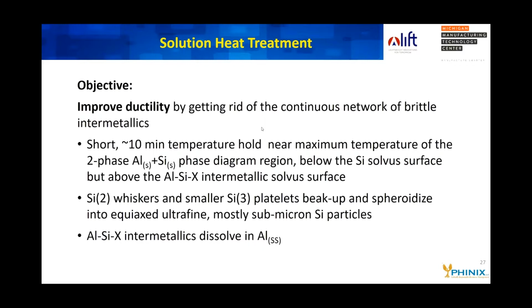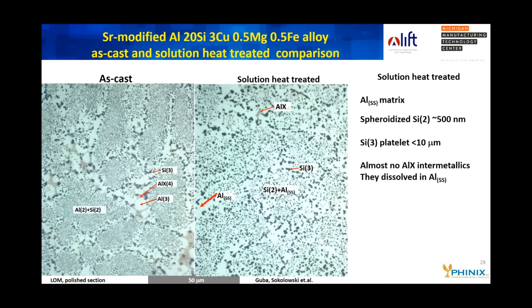So what happens is that silicon whiskers and the smaller Si3 platelets break up and spheroidize into equiaxed, ultrafine, still mostly submicron silicon particles. And the aluminum intermetallics mostly dissolve in the aluminum to form an aluminum solid solution matrix. So here is a comparison between as-cast and solution treated structure. And you can see that the aluminum now is a solid solution matrix that now contains most of the copper, and the intermetallics are mostly gone, dissolved in aluminum.